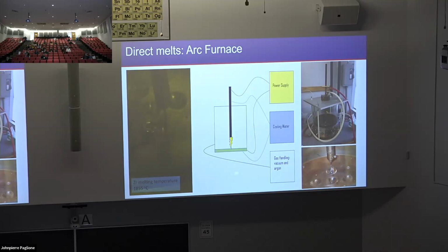The idea here is that in an arc furnace, you'll have a container that you can evacuate and then refill with an inert gas. Going into this will be an electrode that's attached to a welding power supply. There'll also be something like a copper hearth to provide the path for the electrical current. Turn on the power supply, discharge the electrical current through this, and heat things up to really high temperatures over a really short time period.